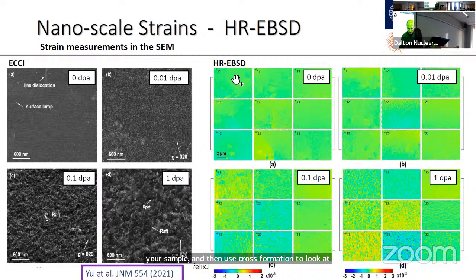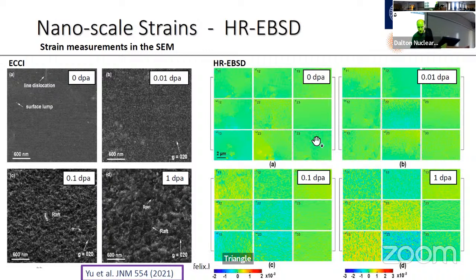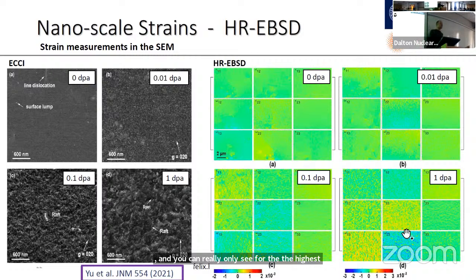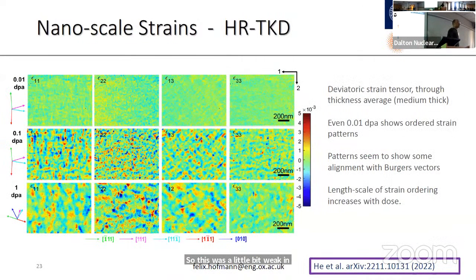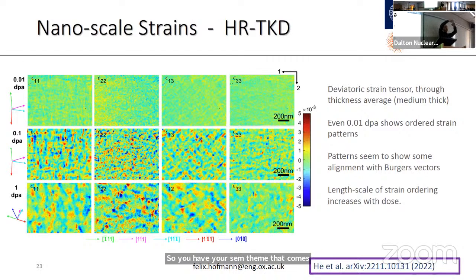And the way this is plotted here is that you have here this upper triangle here, and the diagonal. These are your 6 components of the deviatoric strain tensor, and then down here are your 3 lattice rotations. And you can really only see for the highest radiation dose, which is 1 dPa, you can see that this becomes quite spotty, suggesting that there's a self-organization. So this was a little bit weak in contrast. So we thought, well, okay, let's go and improve on this and actually do transmission Kikuchi diffraction. So you have your SEM beam that comes in, hits your sample, and then you have an EBSD detector that sits beneath your sample. This was done on sample regions, excuse me, about 80 nanometers or so in thickness.